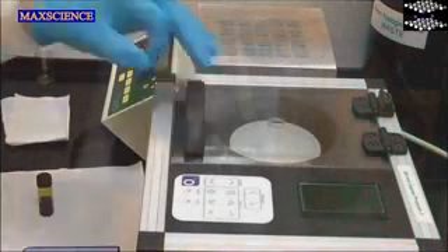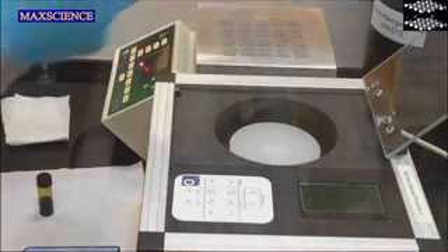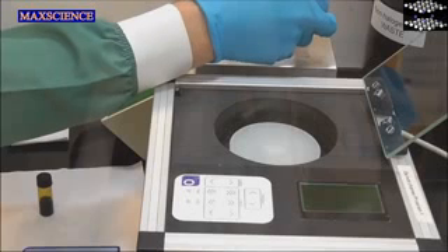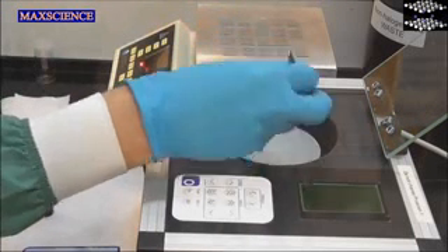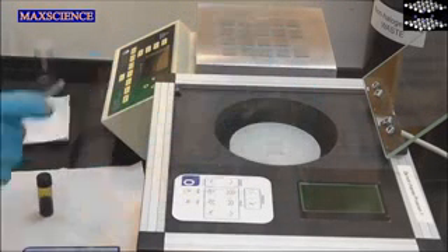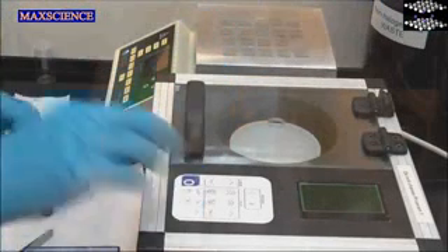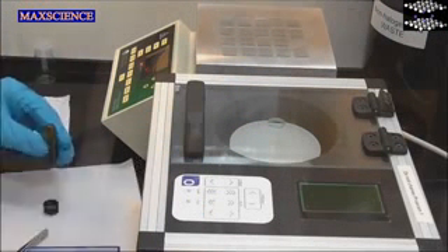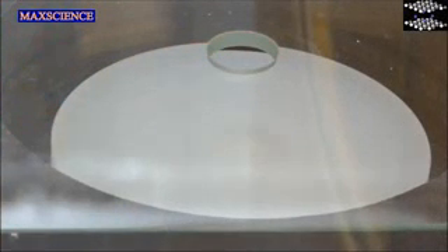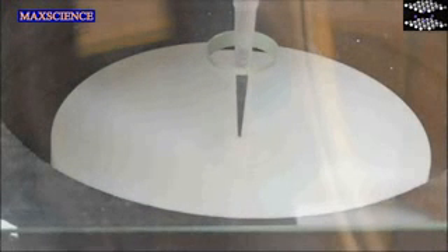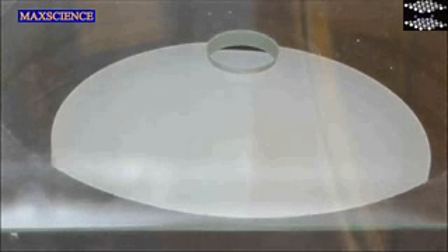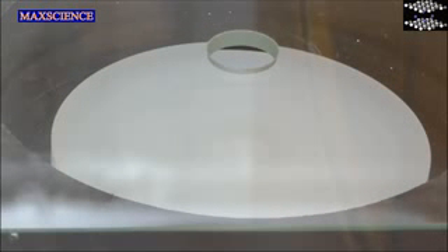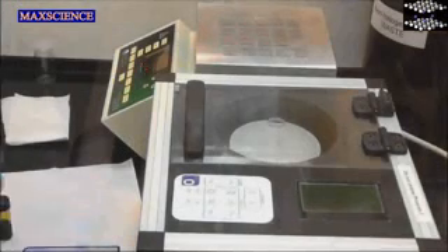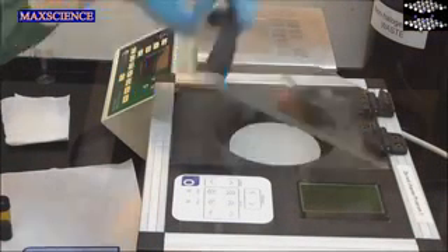To coat PEDOT:PSS onto the ITO, place the substrate into a spin coater and spin at 6000 RPM for 30 seconds. Take 35 microliters of your filtered PEDOT:PSS solution and dispense it onto the substrate, making sure the pipette tip does not touch the substrate. Once the substrate has finished spinning, remove it and place it back onto the hot plate.